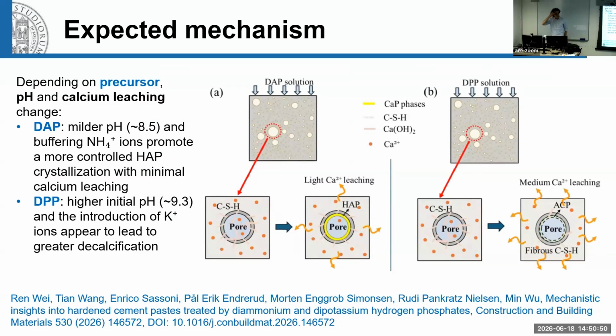In a recent collaboration with some colleagues originally from China, we also tried to clarify the mechanism that is going on in the formation of calcium phosphate if you use DAP as the phosphate precursor. So in the end, the pH of the phosphate solution and also the presence of ammonium ions that can act as a buffer for the pH were found to be important parameters determining the formation of the new phases and also the decalcification of the CSH.